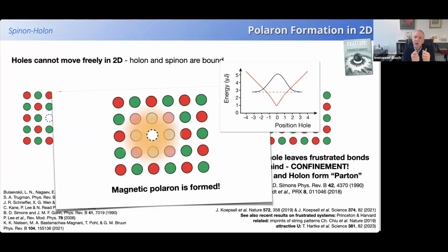If you calculate the energy cost of this hole moving through the antiferromagnetic background, what you actually find in a very simple picture is a linearly increasing energy cost. This should remind you of something in nuclear physics. This is basically what you also have in quarks that give rise to confinement in mesons and baryons, right? So we would also here expect new quasi-particles to emerge from this confining potential. And these new particles that emerge are indeed what we call magnetic polarons.